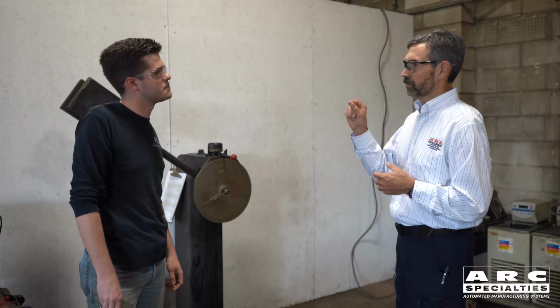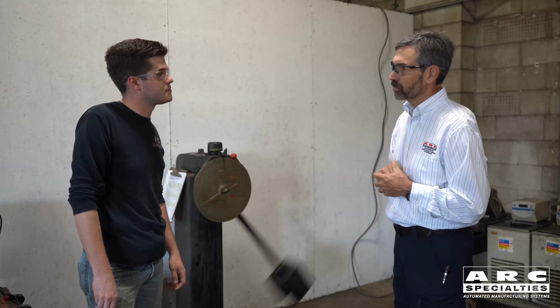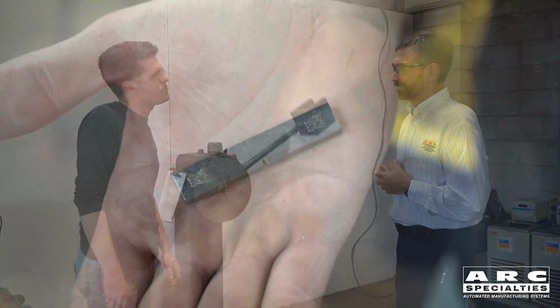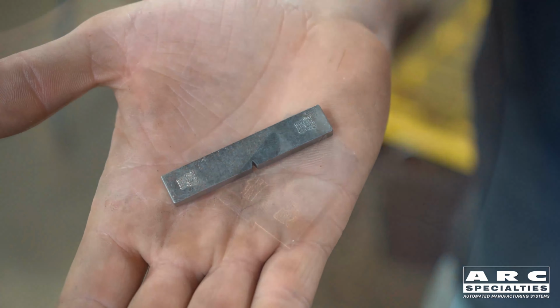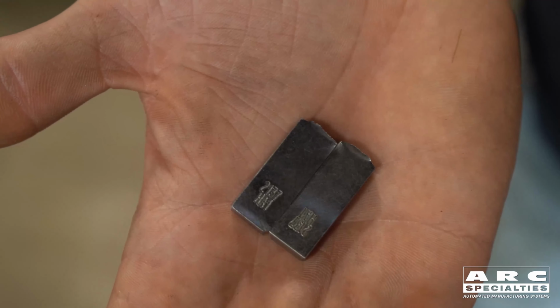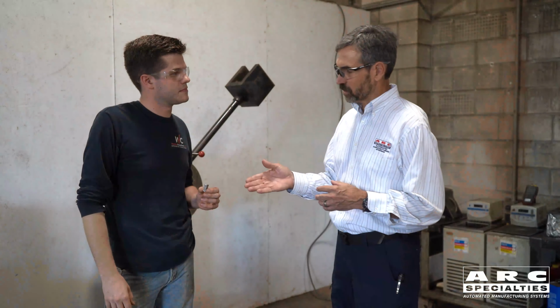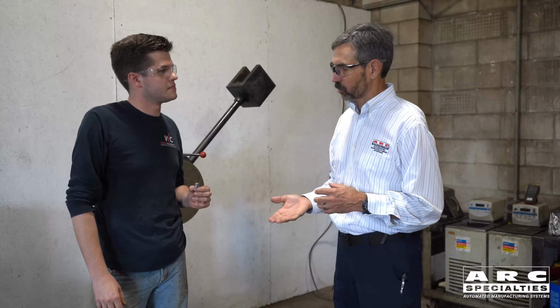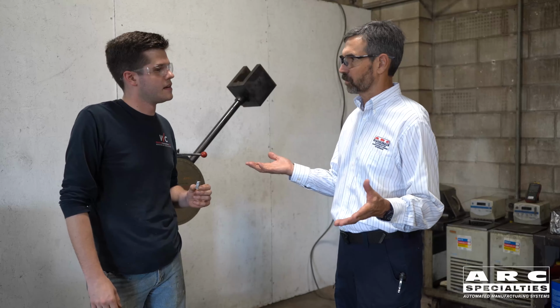So you can change that thickness and you have a ratio that you can calculate. That's correct. So is this an acceptable test or unacceptable? Well, we're not testing for acceptability or unacceptability. We're just identifying materials, just characterizing parts. Okay, so we've broken the sample, we've determined the energy absorbed was 10 foot-pounds. Is there anything else you learned from this test?